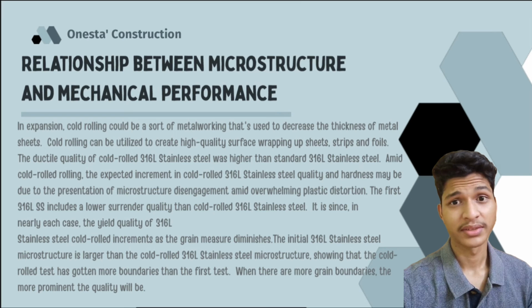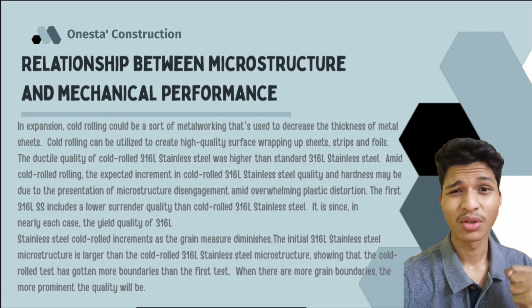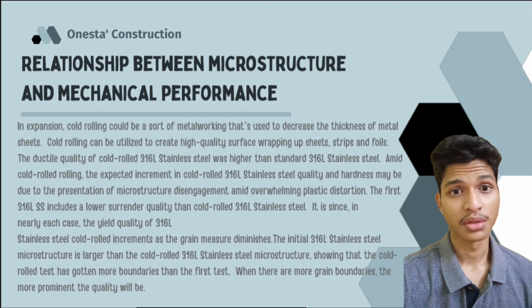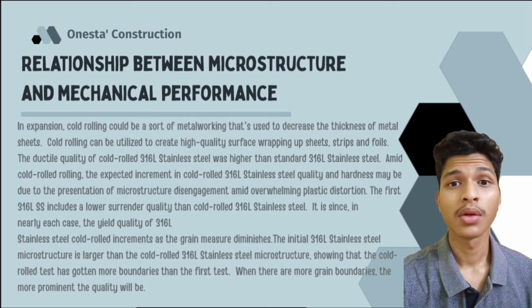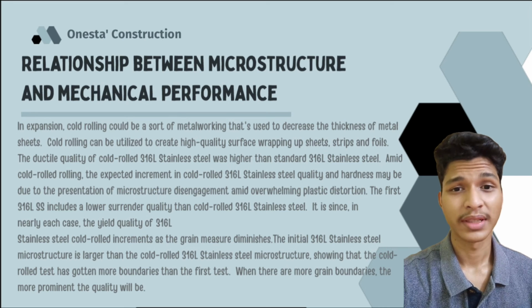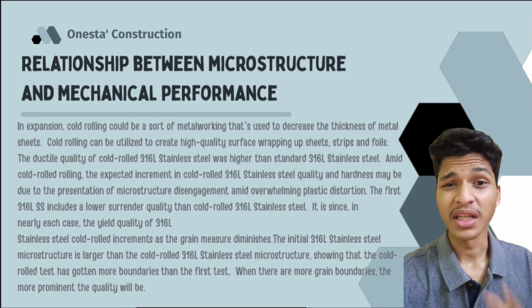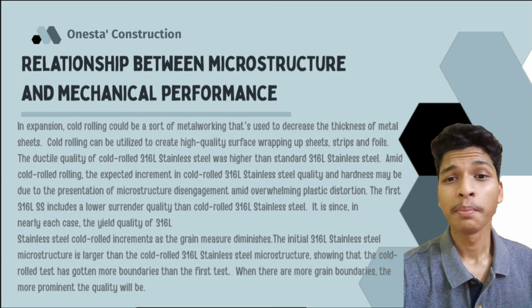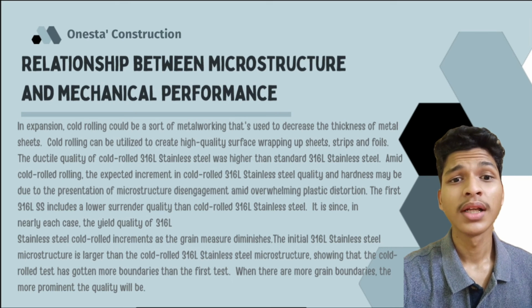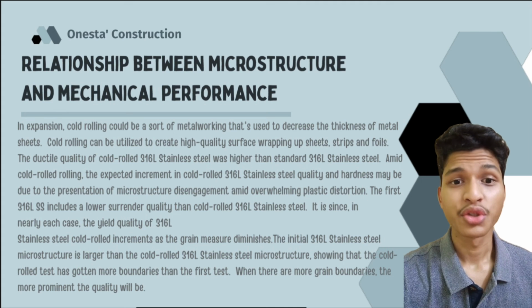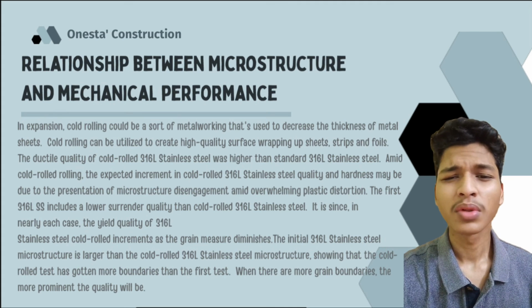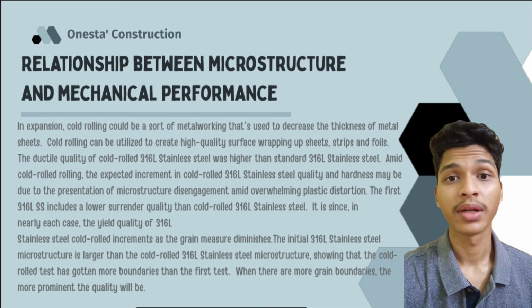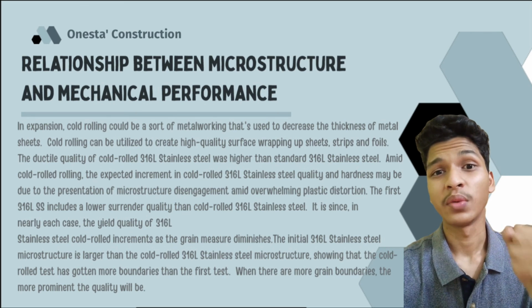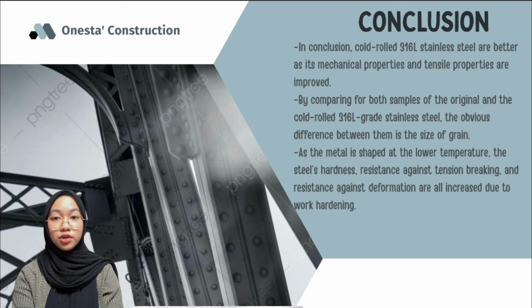The original 316L stainless steel has a lower yield strength than cold-rolled 316L stainless steel. It seems in nearly every case the yield strength of cold-rolled 316L stainless steel increases as the grain size decreases. The original 316L stainless steel microstructure is larger than the cold-rolled 316L stainless steel microstructure, showing that the cold-rolled sample has more grain boundaries than the original sample. When there are more grain boundaries, the greater the strength will be. In conclusion, cold-rolled 316L stainless steels are better as their mechanical properties and tensile properties are improved.